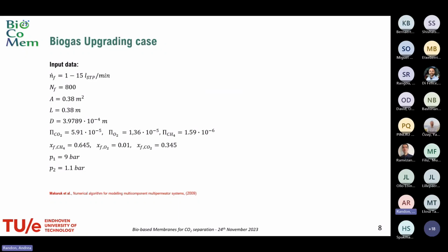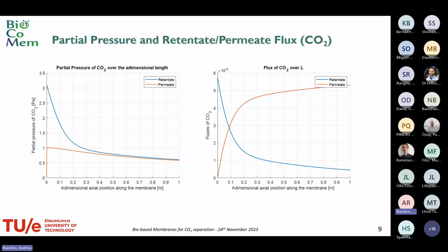These are the input data taken from Makaruk et al. This publication has similar cases to ours, except for the length of the membrane module, which in our case is double. What we did was assess the performance of the model and see if it was doing what we wanted, seeing the variation of the partial pressure, as you can see in the figure on the left, versus the dimensionless axial position along the membrane.